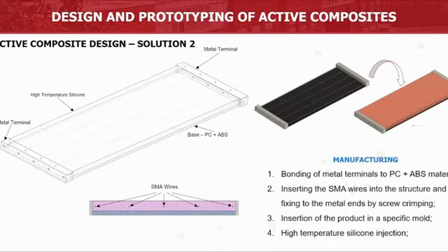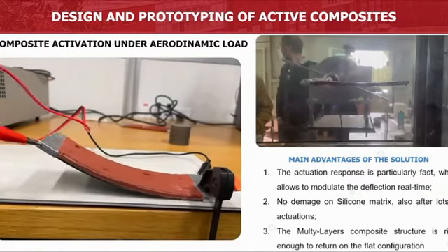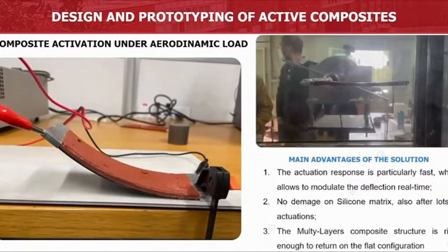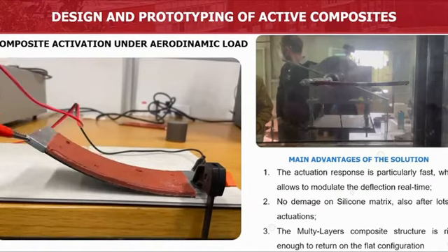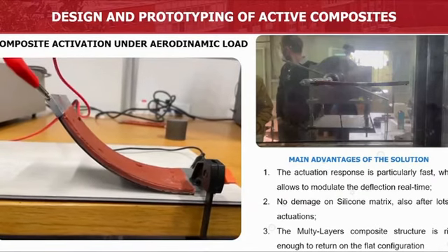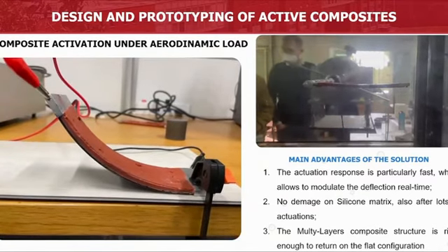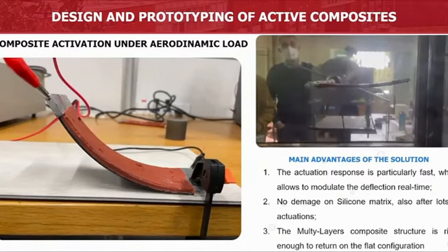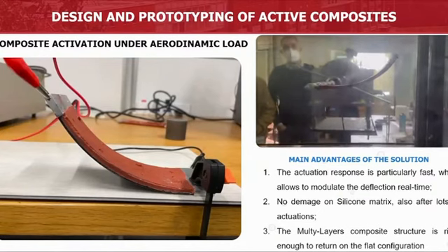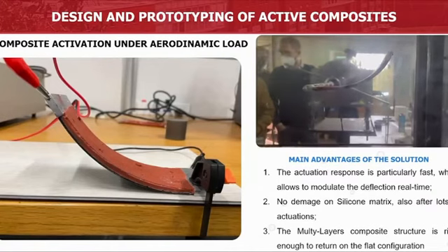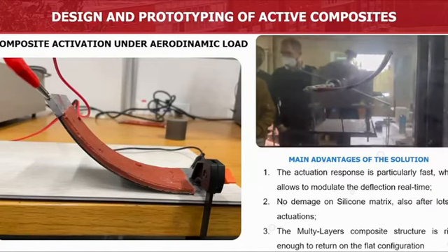So we switched to another solution, solution 2, which is based on an assembly composed of a polycarbonate base plus ABS and 2 metal terminals and a high temperature silicone that covers all the wire. This solution, compared with solution 1, shows lots of advantages, like an actuation response that is particularly fast. You can modify the deflection in real time. No damage on the silicone matrix is encountered, and so the multi-layer composite is a structure able to return to a completely flat configuration.